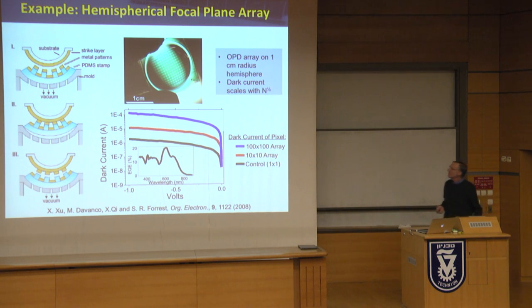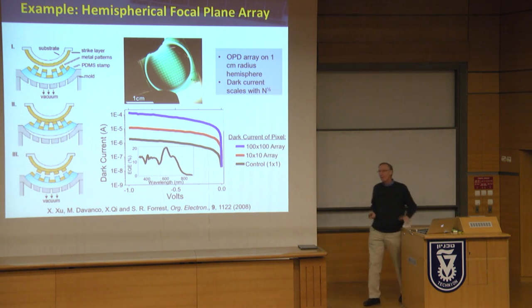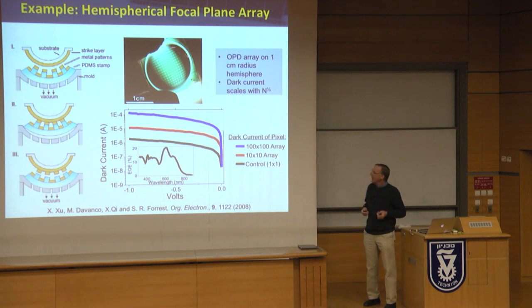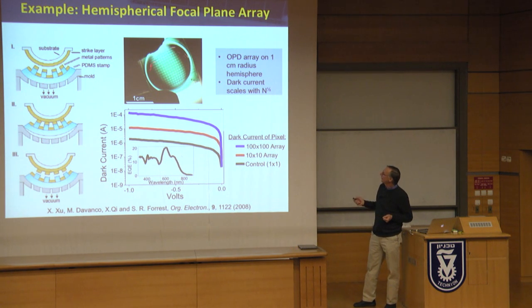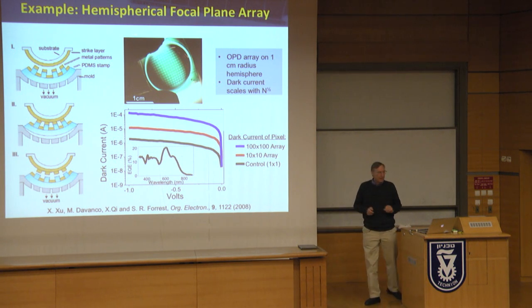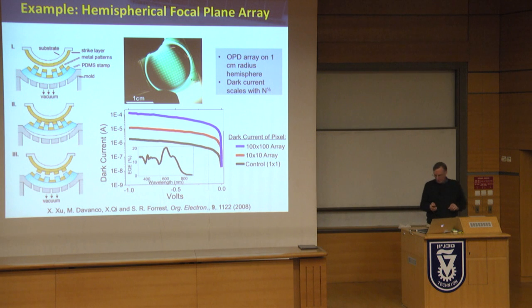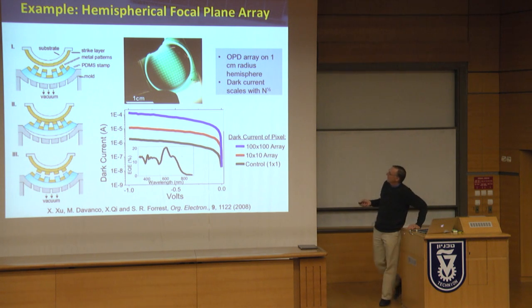So this is just some of the things that we've done. We've made an imaging array of organic devices by cold welding. Basically, we cold weld an array of lines. In one direction, we deposit the organic, and we then turn the substrate over and do it. This was to make an artificial eye type of arrangement, where we just have a single lens.